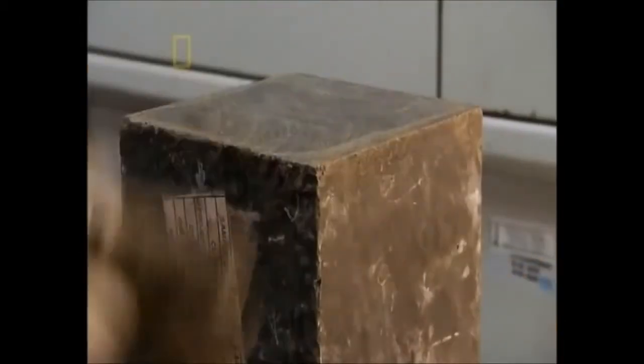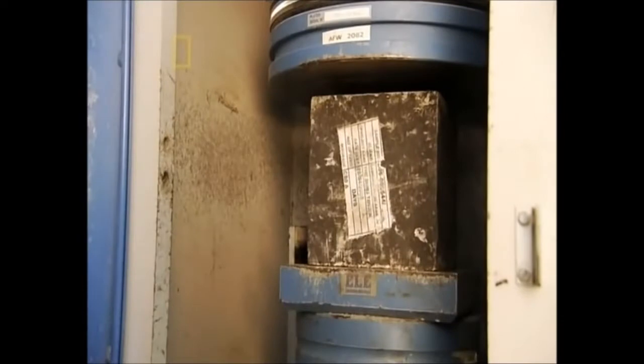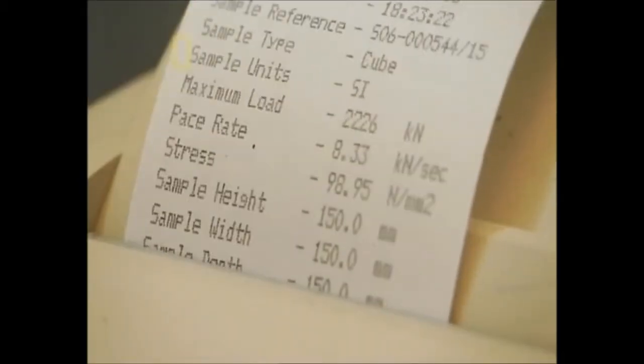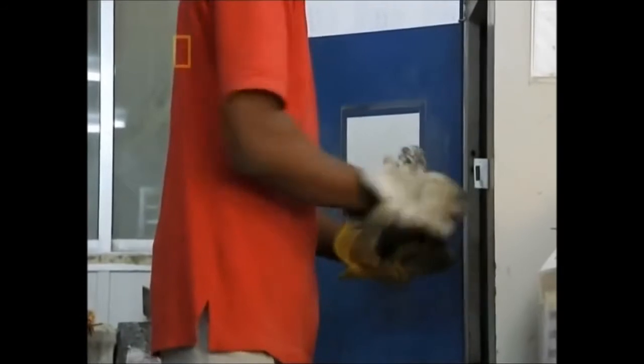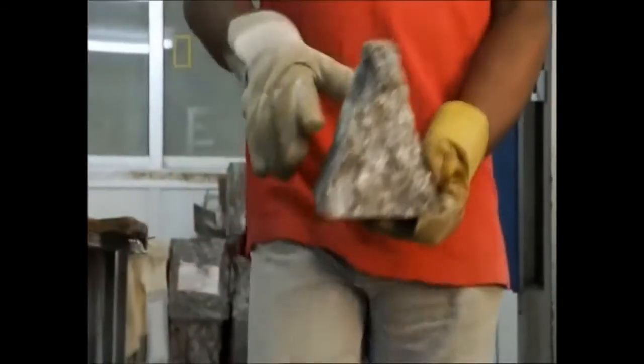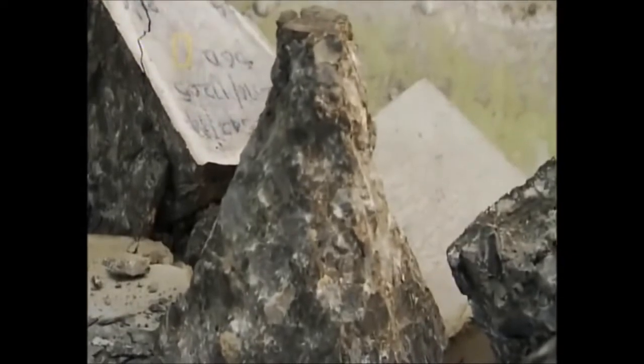To test the strength of the concrete, small cubes are hardened in cool water. Next, the concrete is deposited into a crusher for a stress test. This cube holds up to nearly 14,000 pounds per square inch, making it a high-strength concrete. The concrete test has been successful. But as strong as this formula is, it still has to contend with desert heat.